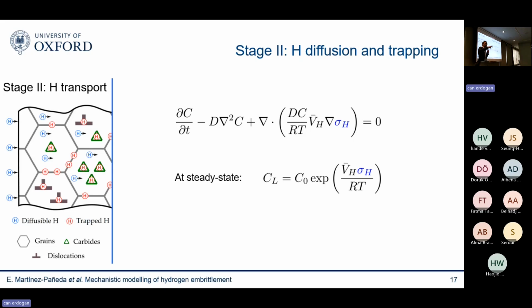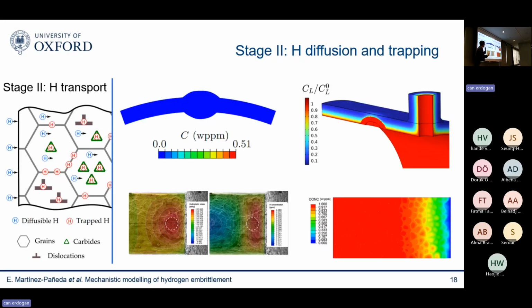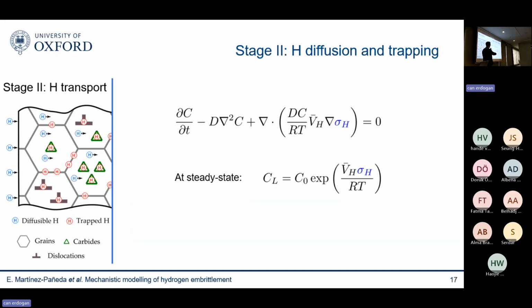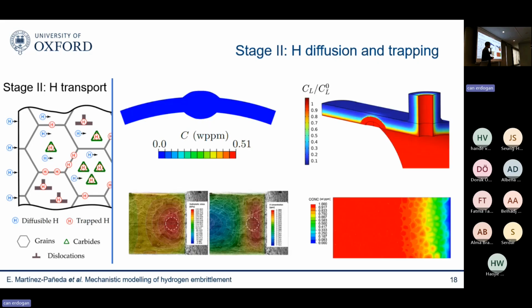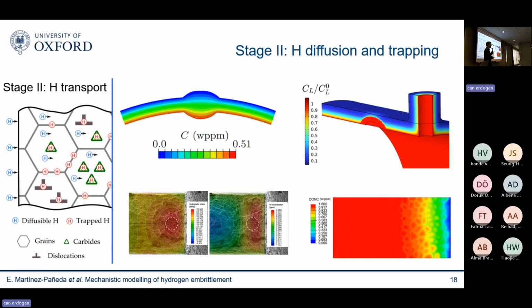Hydrogen not only travels freely through the crystal lattice, it's also sequestered. Basically, if you solve this straightforward equation, a coupled chemo-mechanical problem, in your finite element model, you get something like this. So this is a distribution of hydrogen concentration, for example, in a pipeline with a weld. You can see how as you increase your pressure, the hydrogen diffuses through the weld, and you can do that also at the microstructure scale. So this is relatively well understood.